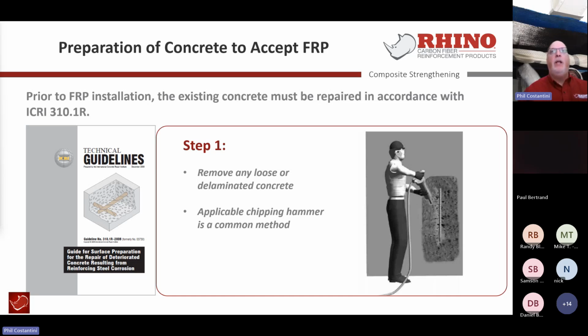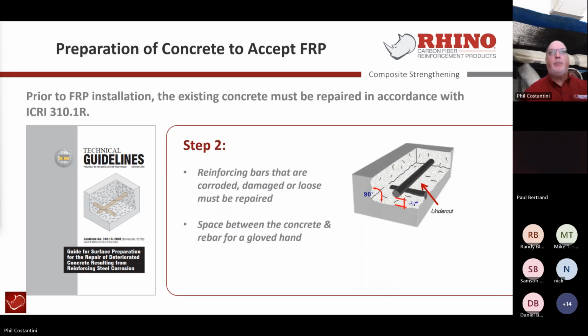Step one, of course, remove any loose or delaminated concrete. If there's partial depth repairs that have to be done, those have to be dealt with. You can do it with diamond grinders, or with a chipping hammer in many applications, but it's important to prepare the concrete prior to any strengthening material. Let's talk about corrosion for a little bit, because that's important. If you're dealing with corroded rebar in the actual application, it's important to detail how you're going to handle that. It's not good enough just to get to the surface of the bar and it's staring at you as a complete little rust ball.